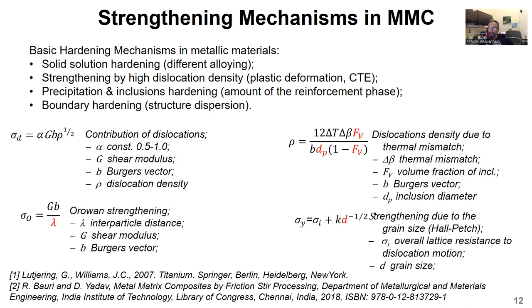From four different possible hardening mechanisms in metallic materials, we believe that solid solution doesn't play a major role in our case since we didn't modify the alloy chemistry. Dislocation density change is usually a result of plastic deformation, which also was not modified during composite fabrication. However, the dislocation strengthening mechanism plays a role when the composite gets plastically deformed. So dislocation pile up will take place at the interface boundary. Such a mechanism certainly takes place during the hardness test.